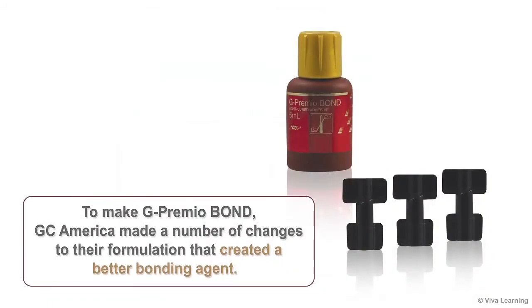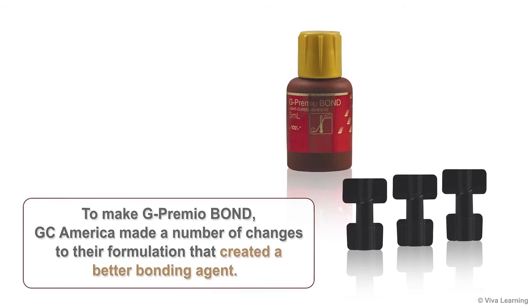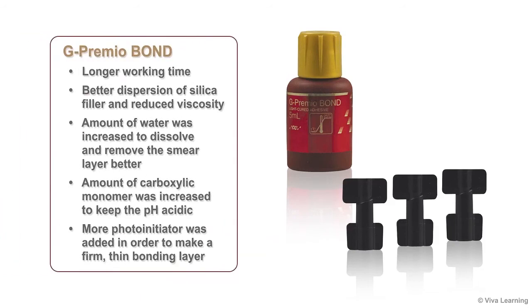To make G-Premio Bond, GC America made a number of changes to their formulation that created a better bonding agent. For example, the longer working time was achieved by improving the dispersion of silica filler and reducing viscosity. The amount of water was increased to dissolve and remove the smear layer better, and the amount of carboxylic monomer was increased to keep the pH acidic. In addition, more photoinitiator was added in order to make a firm, although thin, bonding layer.